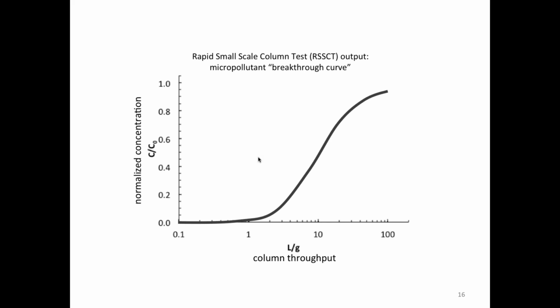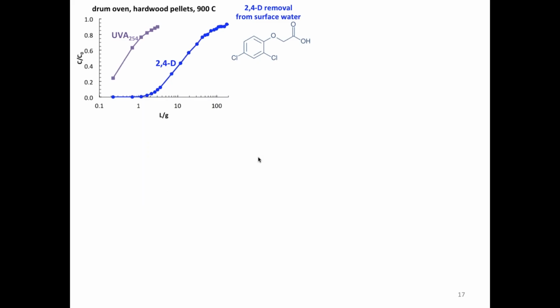Over time, it starts to break through and come out of the column. And then by the end of the experiment, the concentration of the pollutant coming out of the column is essentially the same as the concentration going in, because the material's totally saturated and it's not taking up any more pollutant. So we call this a breakthrough curve. So I'll show a few breakthrough curves.